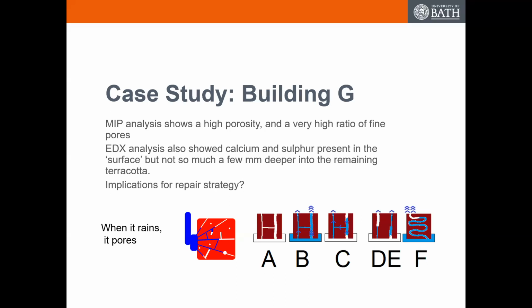It's trapped air. This is the thing we keep forgetting when we're talking about these materials. But I think that's something we should discuss at the end when we have a full discussion about where we go with testing. You think it's trapped air? Oh, I'm sure of it. We don't take enough account of that in our testing. We tend to test wet samples. And in fact, the question I have to ask you at the end is are we overvaluing the value of testing by, for instance, putting pieces in trays where, of course, they can saturate because the air is driven off, whereas when you have things in situ, the air cannot get out so easily.